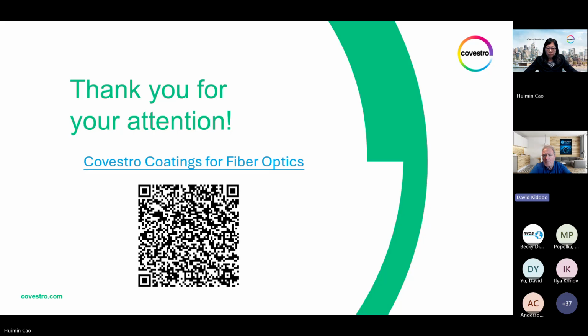First question is, with the range of curing temperatures and fiber drawing processing conditions with conventional coating systems, have you determined an optimum temperature or processing conditions with these new next generation coatings? The new generation coatings are designed capable of handling hotter and hotter glass. But in terms of the cure speed, if you want faster cure speed, really you prefer a cooler glass, which traditionally it is 50 degrees C. I mean, your die temperature is set at 50 degrees C.